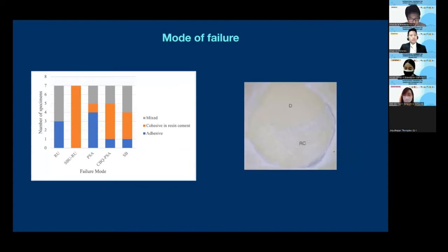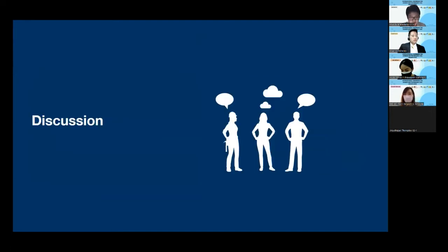For the failure mode, it was shown in the graph here. Group 1 and group 3 show mostly adhesive and mixed failure, while group 4 and group 5 mostly showed cohesive failure and mixed failure. And group 2 found only cohesive failure in resin cement.